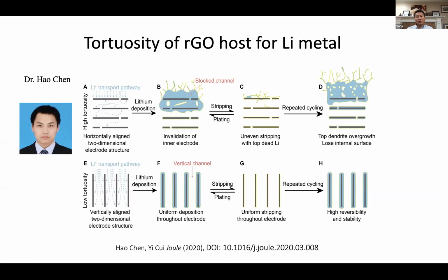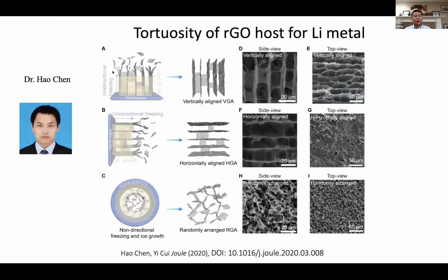It's still dependent. We actually produce this using a freezing method and a graphene oxide solution. If you freeze from the bottom, ice crystals nucleate at the bottom, right? This is an aqueous solution. You can vertically align graphene. If you cool it from the side, you horizontally align. If you cool it in a surrounding way, it's going to be randomly aligned. So we generated different alignment orientations, vertical, horizontal, and random, and compared their electrochemical behavior.